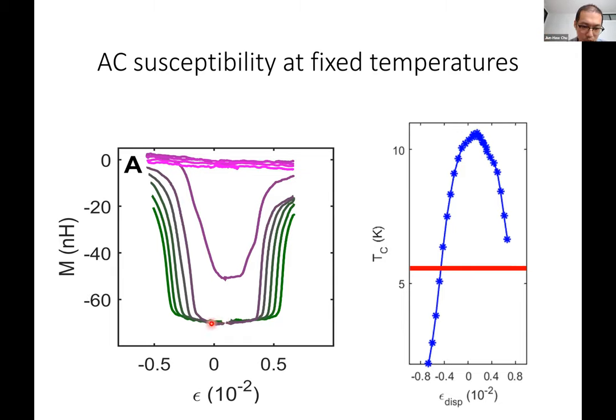By applying either positive or negative strain, you can drive the system out of the superconducting state, and the Meissner state goes away. So you see a large increase of the magnetization, and the strain required to push the system out of the superconducting state becomes lower and lower with temperature. Of course, once you go to high temperature, you're in the metallic state and no longer have the Meissner response. So this further confirms that what we're seeing is not just some weird conducting path on the crystal, but really a bulk phase transition of the superconductor.